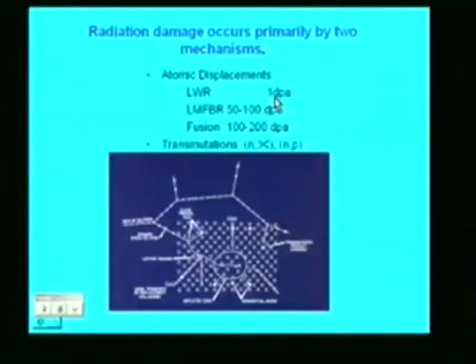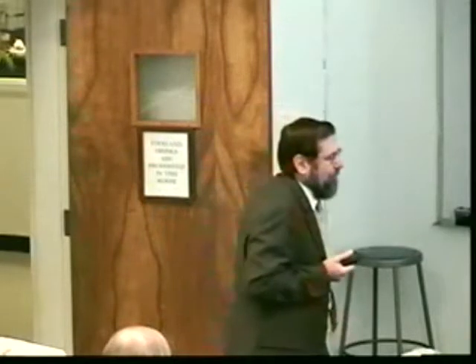What saves us in an LWR is usually that the materials that are in the very high flux region don't stay there very long. At the fuel cycle, you change them out. On the other hand, on a liquid metal fast breeder reactor, there are a lot of structures that remain longer and are in a very high flux region, so we get damage levels of 50 to 100 dpa. These numbers sound small, but it means every single atom on the average is knocked out of its lattice site 100 times during the life of the material.